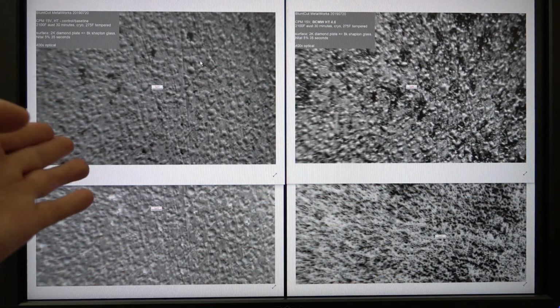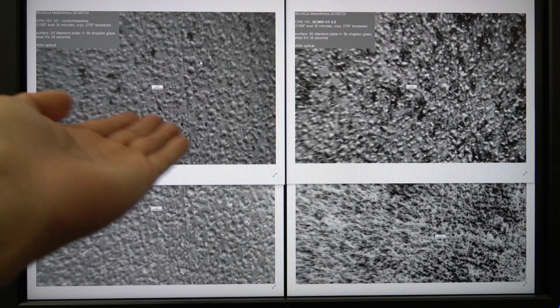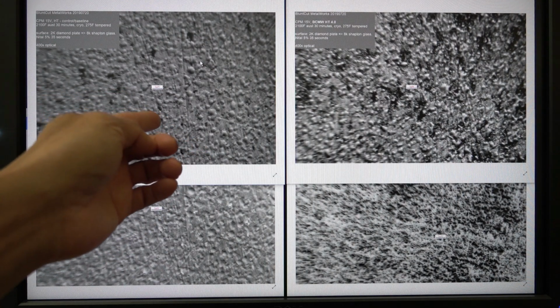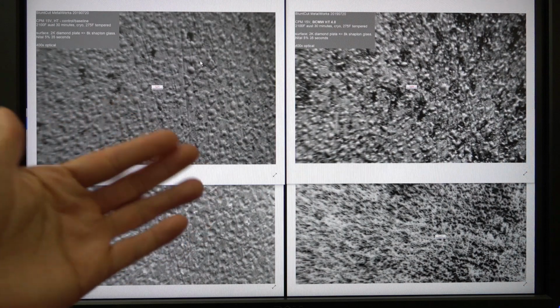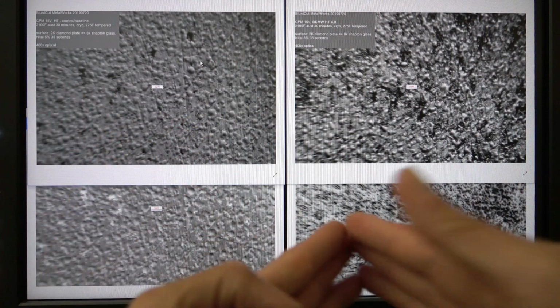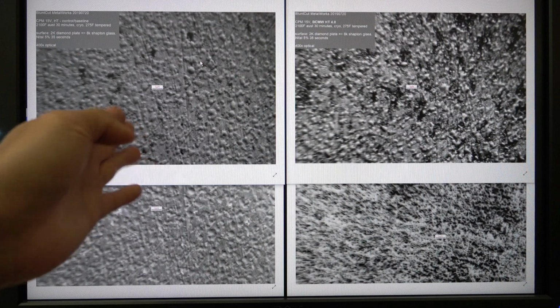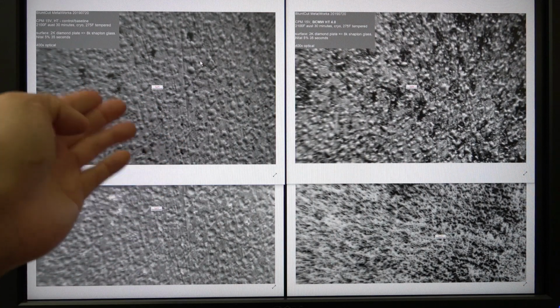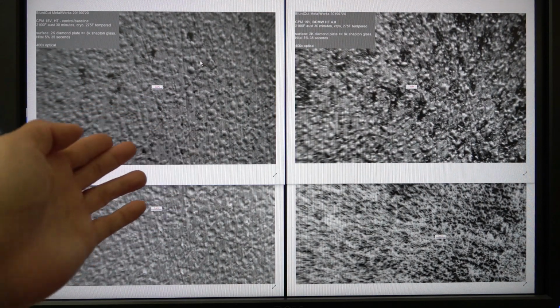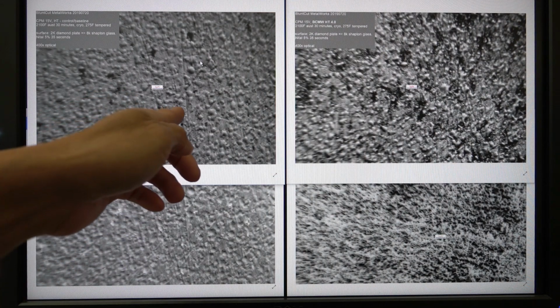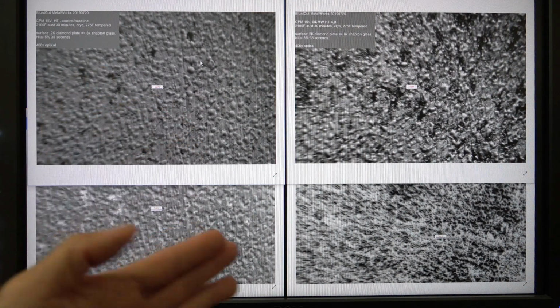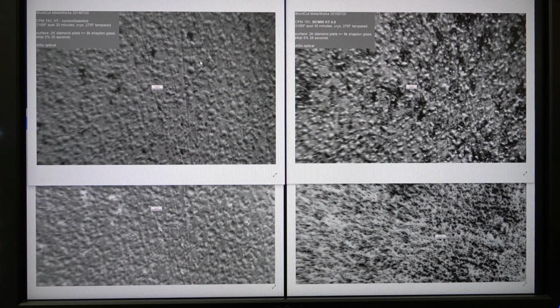If you sharpen your knife really sharp for this kind of matrix and carbide, then you will lose it quickly, because again, when you have a thin cross section, you don't have the support to hold on to the carbide. It will fall off and be replaced with the burnishing effect, which is, in this case, smooth matrix, rounded edge. And that's why people experience a quickly dulled keen edge.